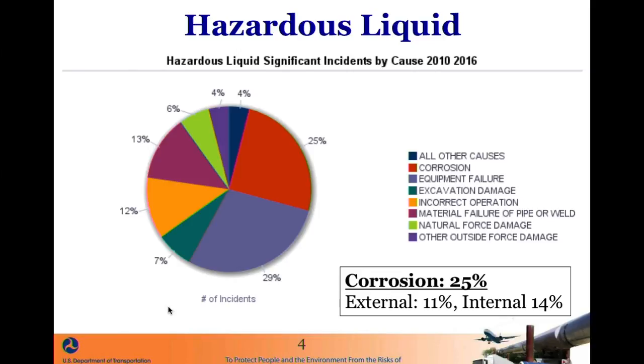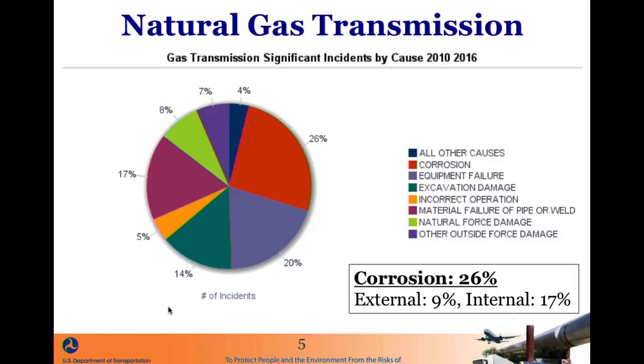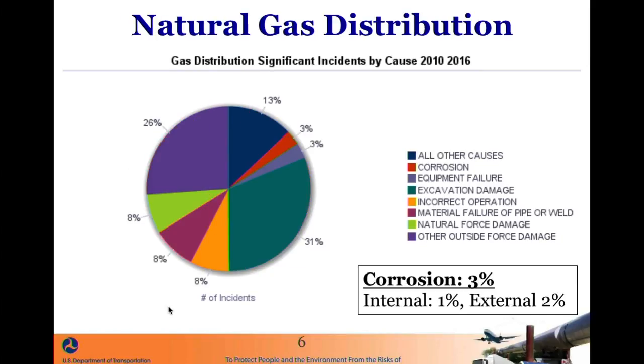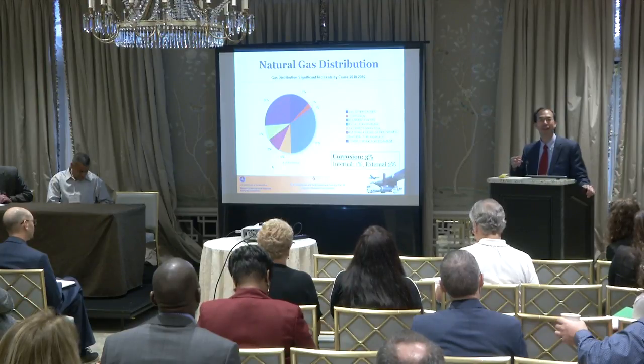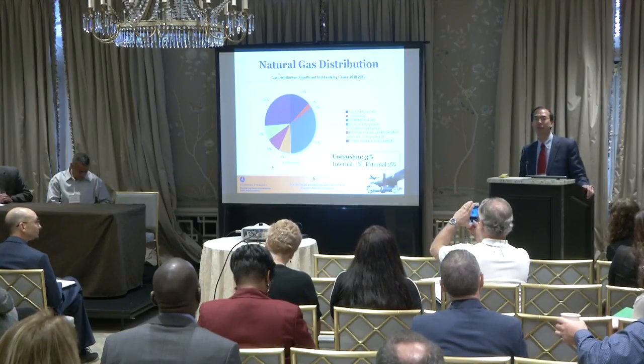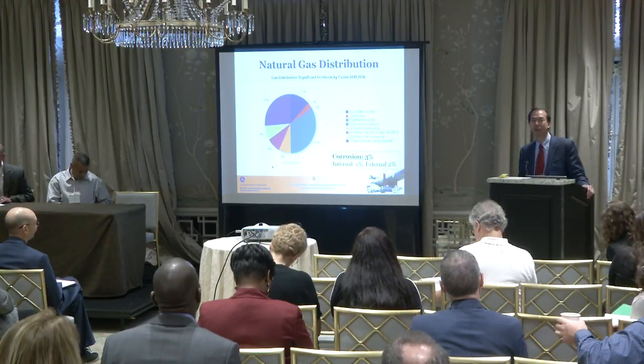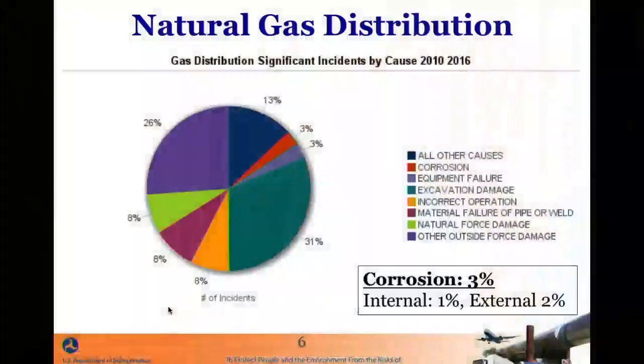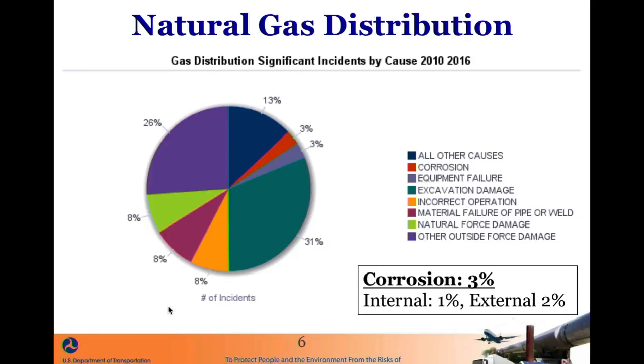So this is for hazardous liquid lines. It's similar for natural gas transmission. You see, 17% of significant incidents were caused by internal corrosion. And then here is gas distribution. Can someone tell me why the corrosion rates are much lower with gas distribution? Anybody? Yes, there's a lot of plastic pipe that's used, and plastic does not corrode. So that's one of the great things about plastic. The main downside is it's much weaker than steel, so it's less practical and economical to build a large diameter, high pressure transmission line out of plastic. So corrosion is much less of an issue with gas distribution systems in general.